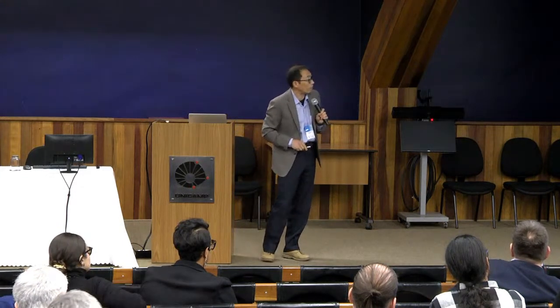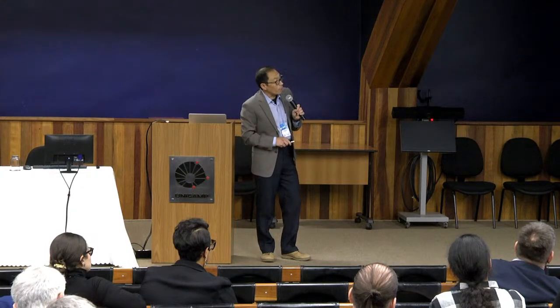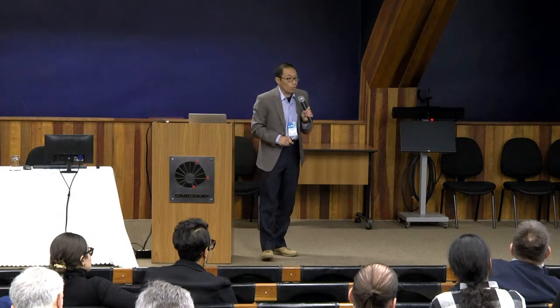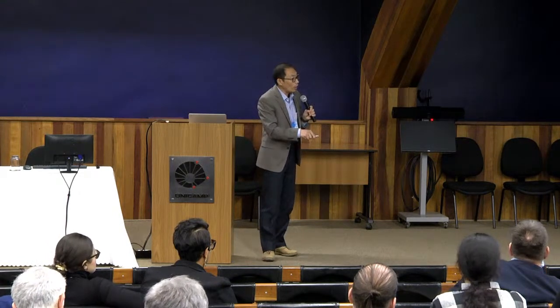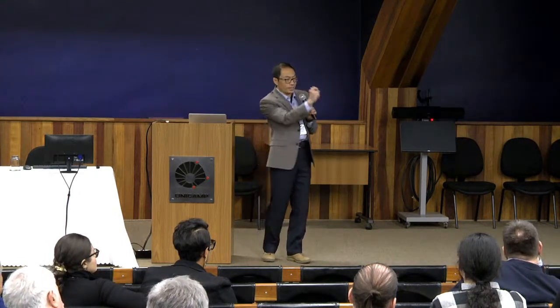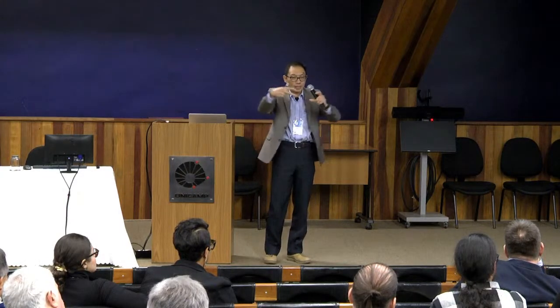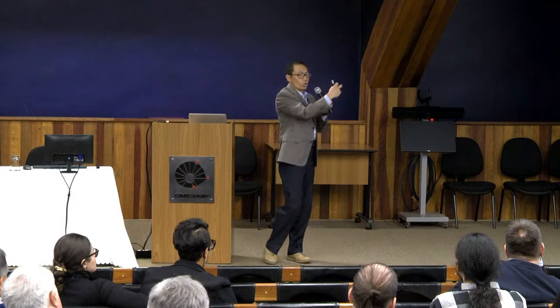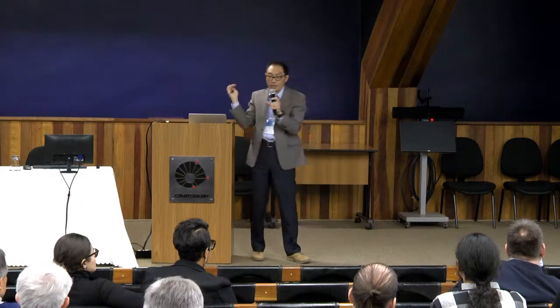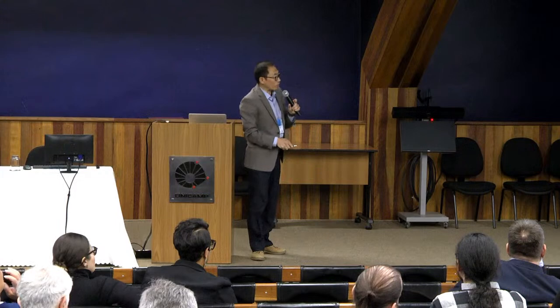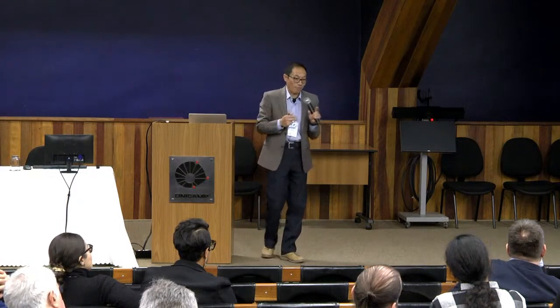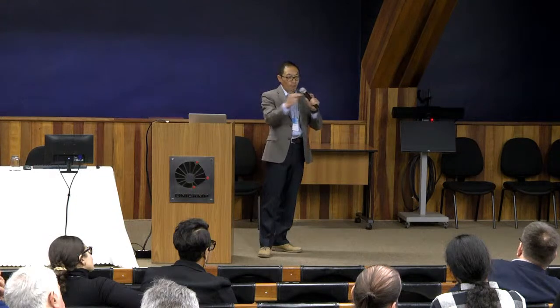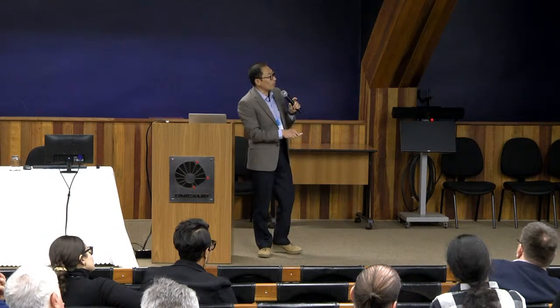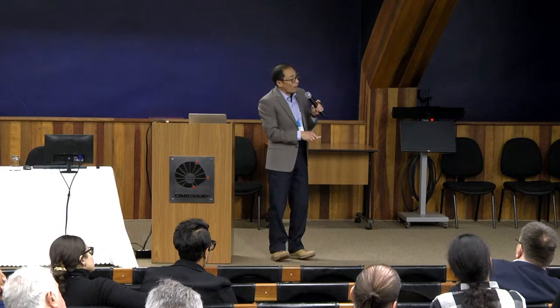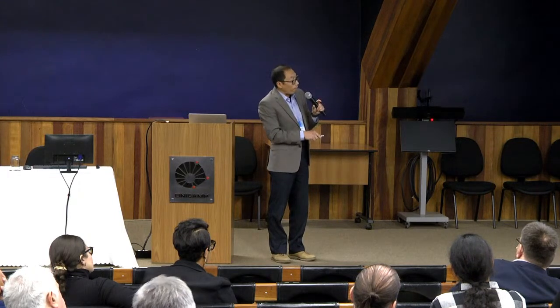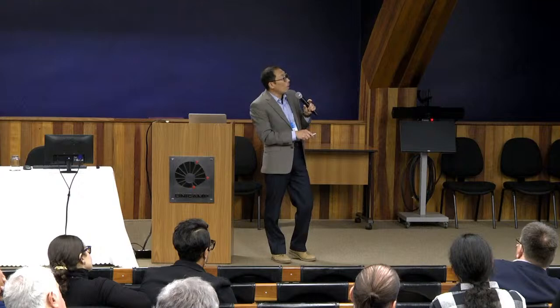The other thing is this feature. We were fortunate to have an amazing set of material from Argonne National Lab. A typical lithium nickel oxide is always a mixture of nickel and lithium because of the size of the ions. They are very close. When you synthesize, it's very hard to push all the nickel into the nickel layer and lithium into the lithium layer. They always mix. But they were able, I don't know how, to make a perfect, almost perfect lithium nickel oxide.